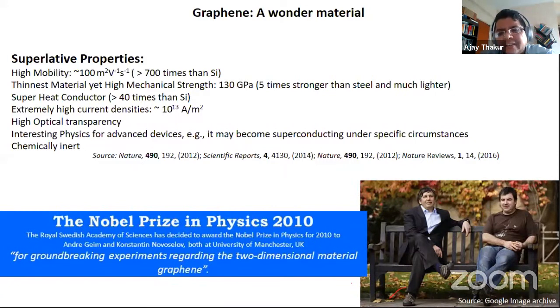So it turns out that even this graphene, which Novoselov and Geim made, is stable on a substrate. Eventually you need to put it onto a silicon dioxide substrate, where the substrate bears a lot of the elastic energy cost, thereby ensuring that the thermal fluctuations do not lead to disintegration of this carbon layer.